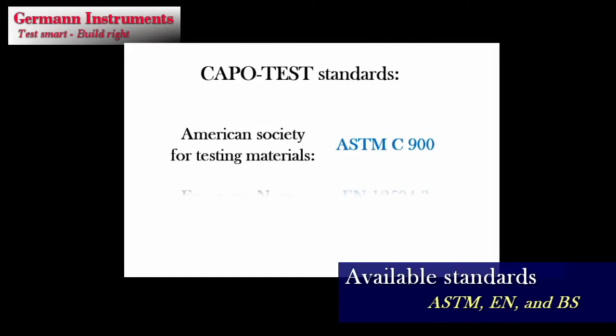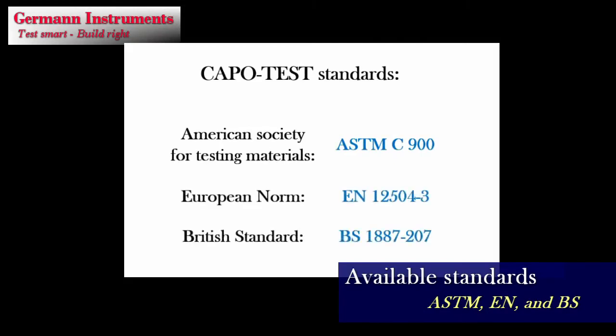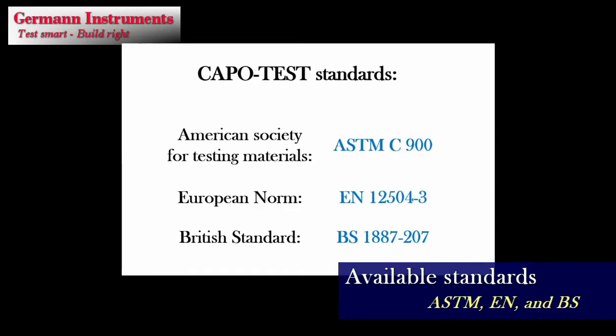The CAPO-Test is the most accurate test system for in-place strength available today, covered by ASTM C900, European norm EN 12504-3 and British standard BS 1887-207, and can be used with great confidence on all types of normal concretes without correlation to drilled-out cores. For a trained operator, one CAPO-Test takes about 15 minutes. All equipment is portable, there is only minimum damage to the structure that can easily be repaired, and the test result is immediately available. No water and electricity supply are required.